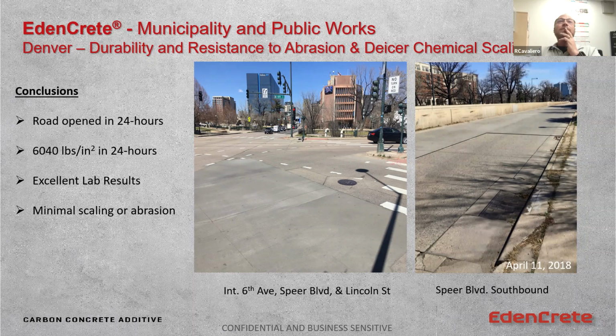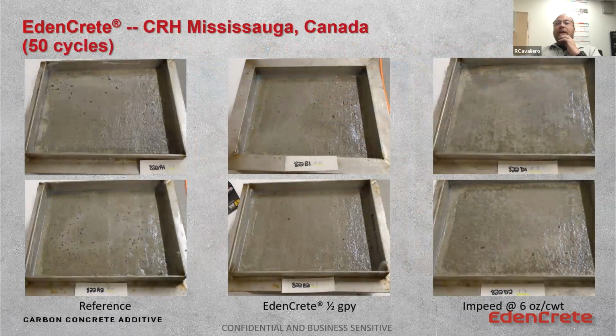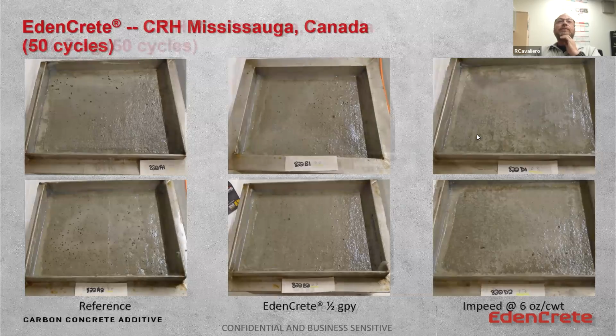And in spec work. This was another one where we achieved the design strength in only 24 hours, and it was supposed to hit it in 72 hours. So they were able to open that section of concrete 2 days sooner than they would have originally. Again, de-icer chemical scaling against something like Impede. You can see not a lot of scaling here, and the EdenCrete works as well as an integral waterproofer.